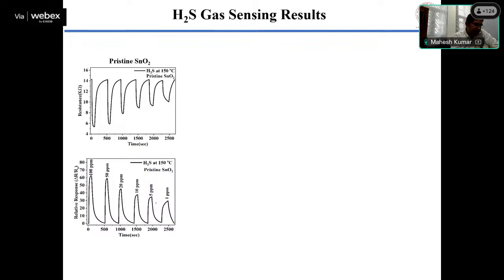You can see that at different concentrations, this gives a very nice change in the resistance. Here is the relative response. That means we calculate the resistance in gas minus in air, divided by R_A. From this we can calculate the response, which we call the relative response.